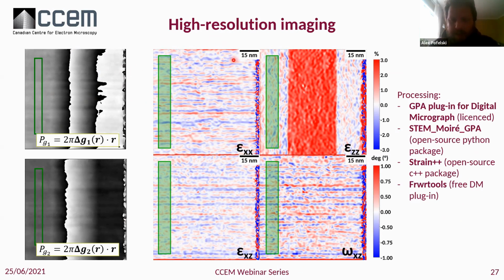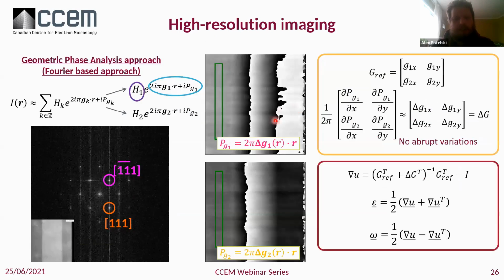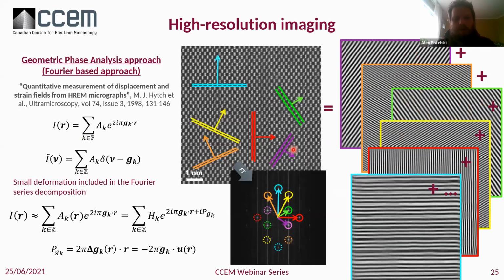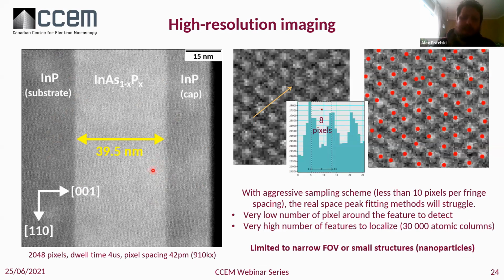And this is what we get here from this indium arsenide phosphide sample. Again, we're going to be using this sample all along now. And as expected, we have no deformation anywhere, just deformation along the growth direction. One thing I didn't mention is that the image is rotated by 90 degrees to align the growth direction along the horizontal scanning line here.